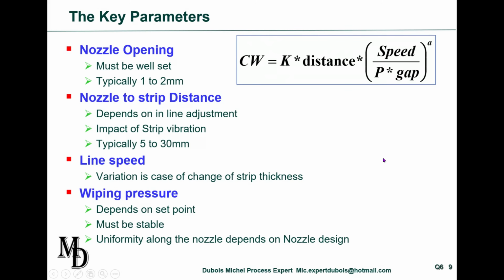Yes, I wanted first to remind you of the key parameters. As I said, it's exactly the same as what I said on the previous question. Of course, the key is nozzle opening. It's not always easy to have a constant nozzle opening of 1 or 2 millimeters. The nozzle to strip distance, it's clear. And keep in mind that the nozzle to strip distance, of course, depends on strip vibration, as I told you. And it depends also on the line adjustment. The typical distance is between 5 and 30 millimeters nozzle to strip.